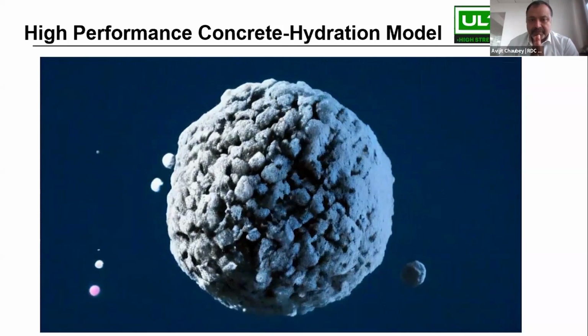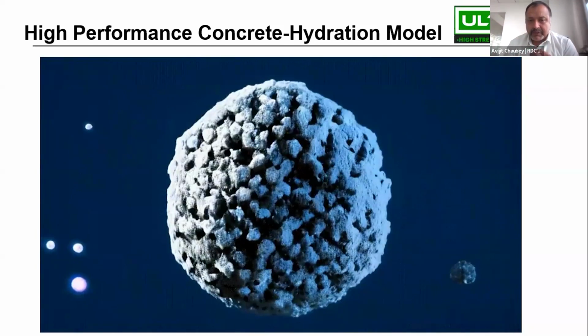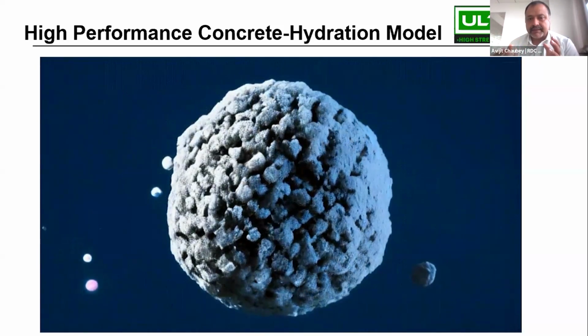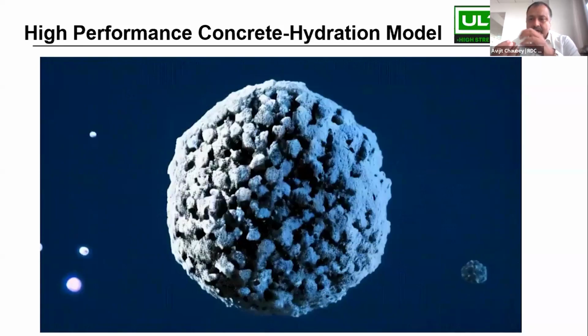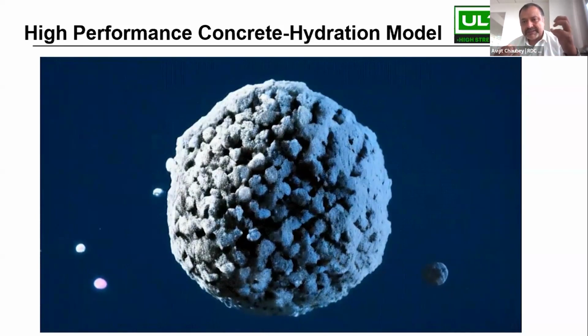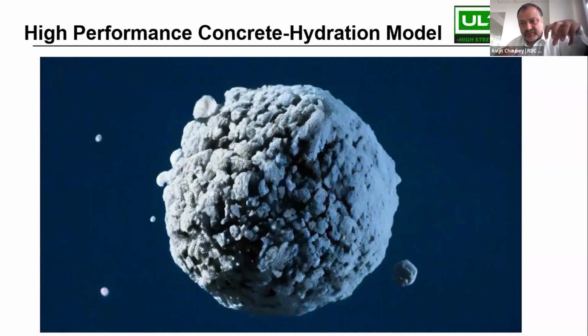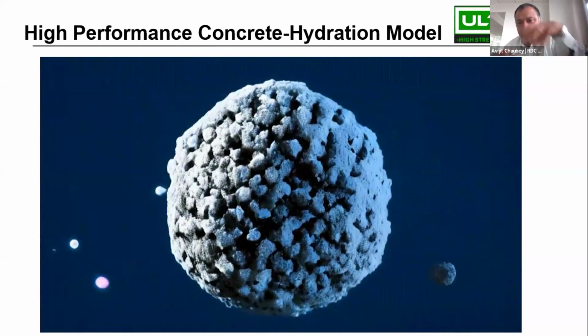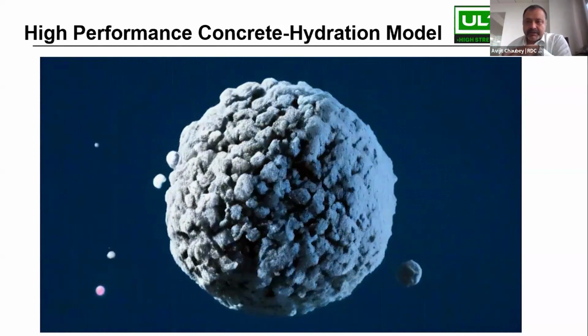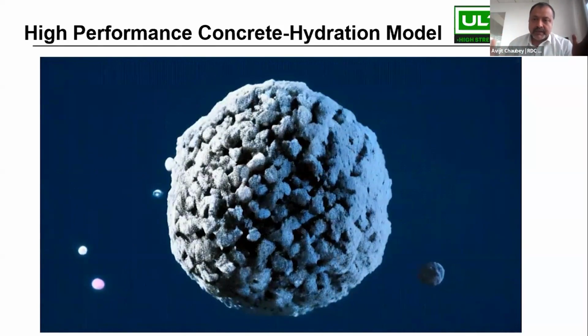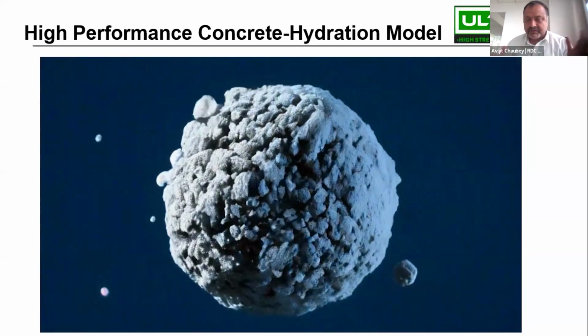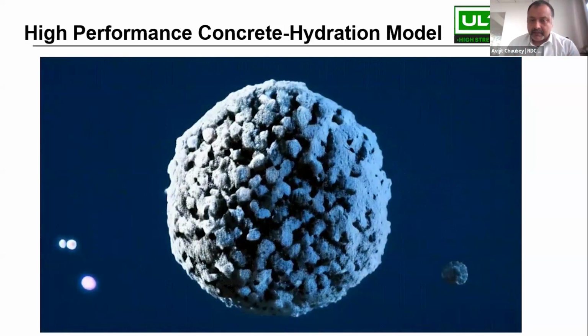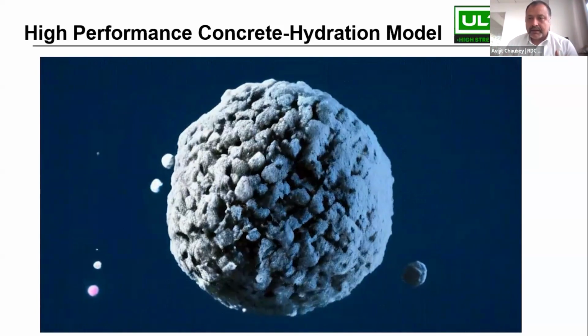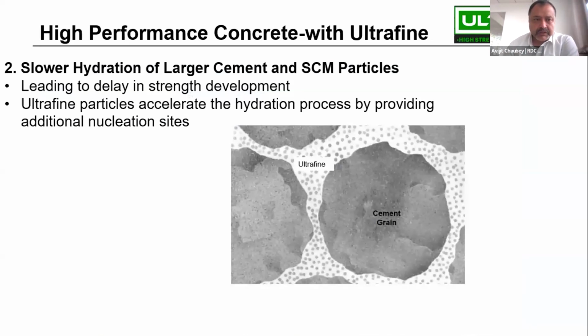Thereby, after some time, the cement particle is not able to hydrate because it is getting covered with CSH. Now, when we have ultrafine materials, we have been able to find certain materials which act like nucleation sites. So the CSH gel, instead of precipitating on the cement particle, precipitates on the ultrafine particle. This way, more and more CSH is formed at early age, and you are able to get a higher strength. So this is exactly what I've been trying to tell.